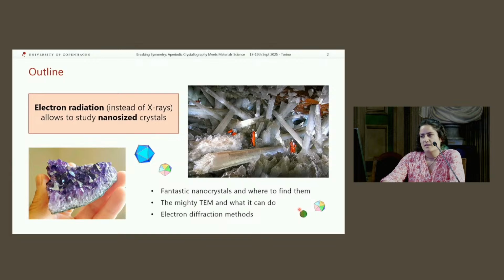So we are using electron radiation, which interacts with matter much more strongly than X-rays. So this means that we can get meaningful data, so strong enough data with good information, also from nano-sized domains of our sample. So we are talking about samples smaller than 1 micron.